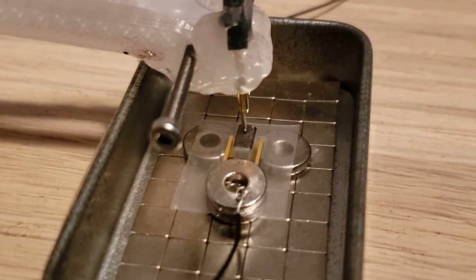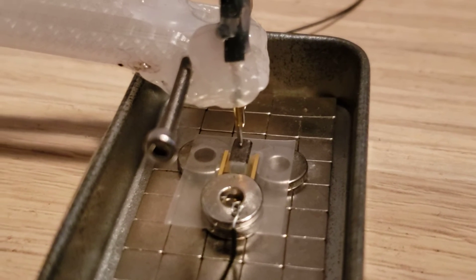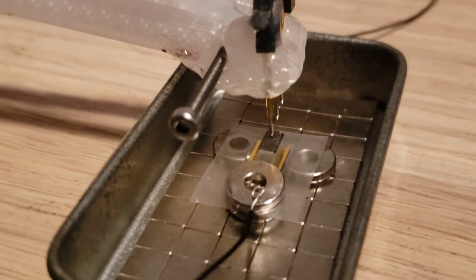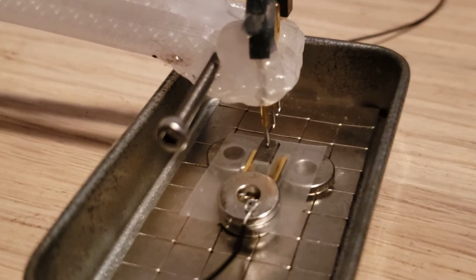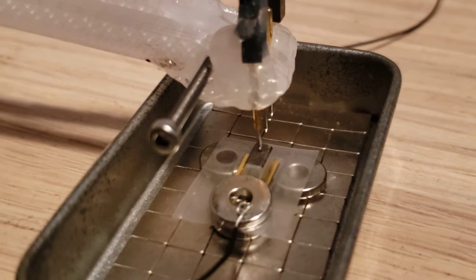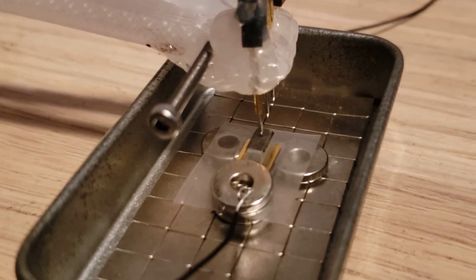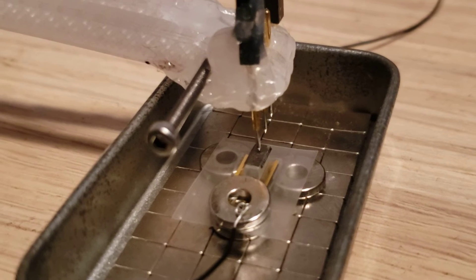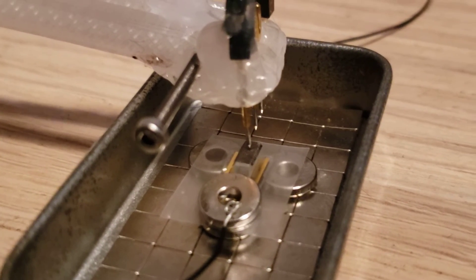What I'm attempting to do with this setup is induce a ferroelectric change in the crystal that has periodicity matching the periodicity of the bottom electrode, so 10 micron spacing. This is a process called periodic poling, and it can be done on a variety of non-linear crystals provided they have ferroelectric domains. KTP is one of these crystals.